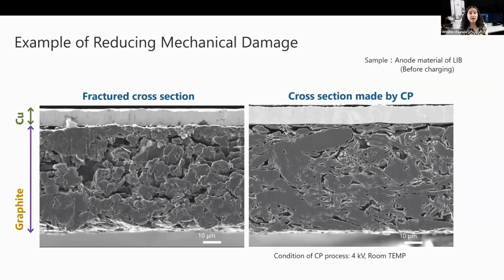This example demonstrates how JEOL's cross-section polisher can significantly reduce mechanical damage in cross-sectional imaging of battery samples. The sample shown is an anode material prior to charging, where air isolation and cooling are not required. On the left, a fractured surface reveals irregularities in large voids caused by mechanical stress. In contrast, the CP prepared cross-section on the right exhibits a much smoother surface. The copper grain structure is visible, and the interface between the copper and graphite can also be clearly observed.